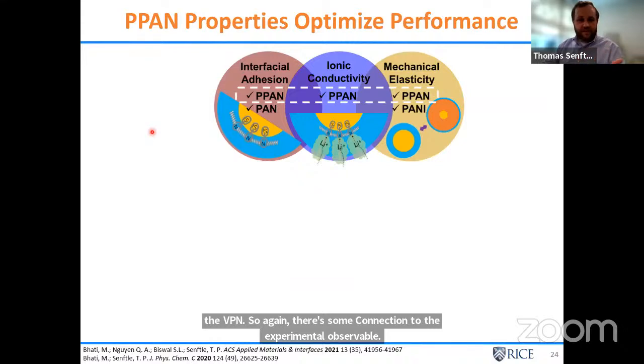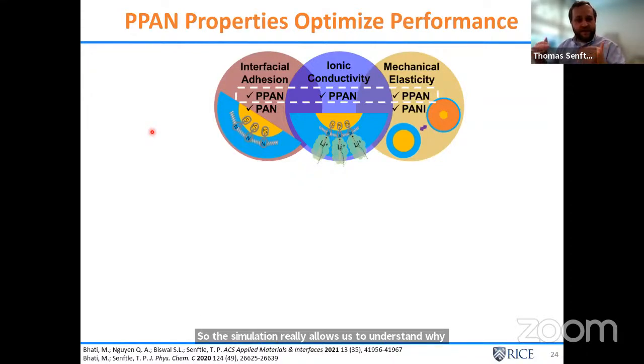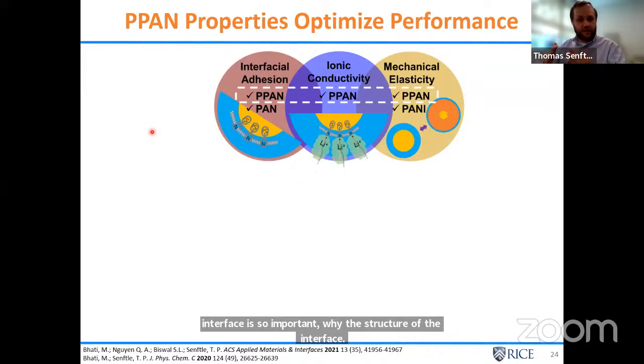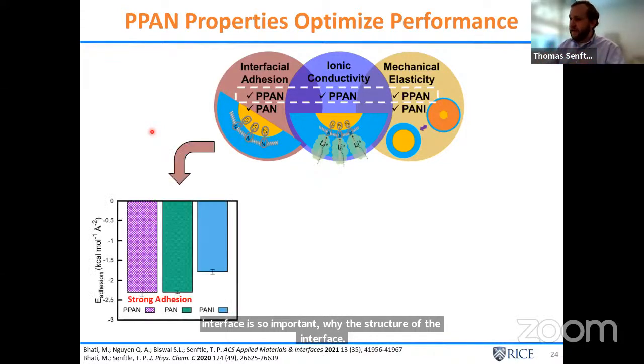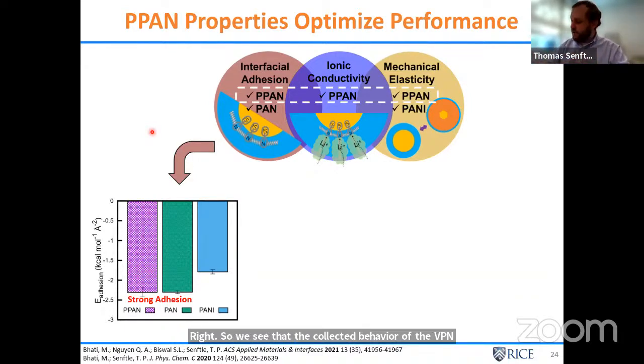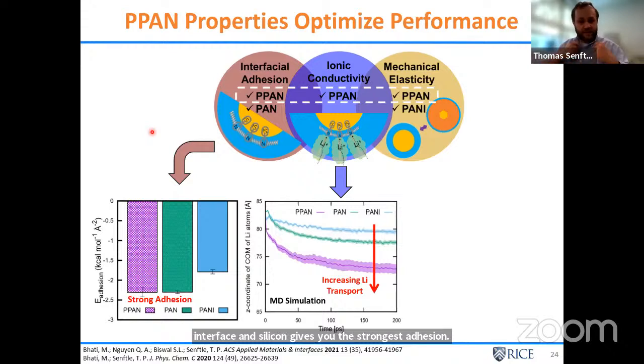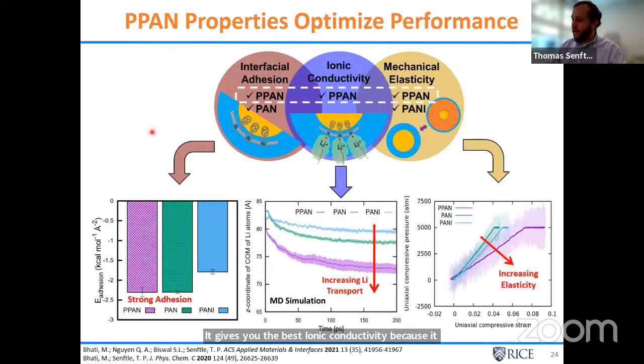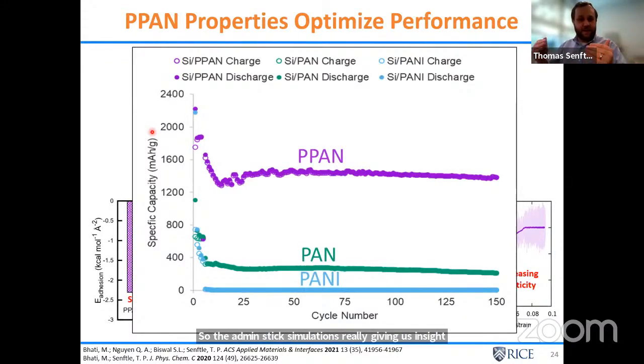So the simulation really allows us to understand why the interface is so important, why the structure of the interface gives you the properties that are really essential for the battery performance, right? So we see that the collective behavior of the p-pan interface with silicon gives you the strongest adhesion. It gives you the best ionic conductivity because it creates these highways for the lithium. And also it's the most flexible. So the atomistic simulation is really giving us insight into experimentally why this particular p-pan binder outperforms some of the other binders. And we can then go back and use that to now design better binders for these composite systems.